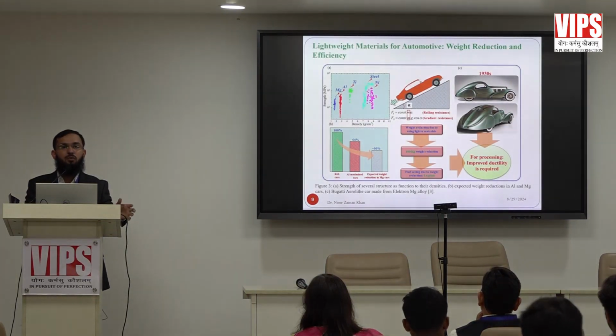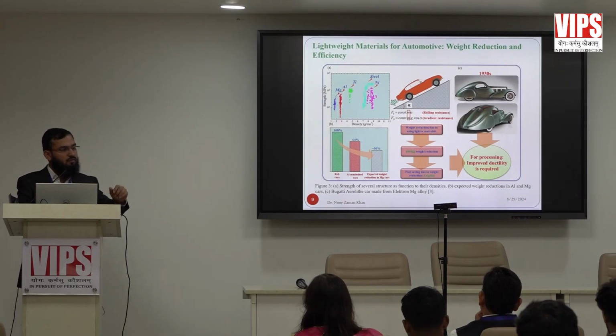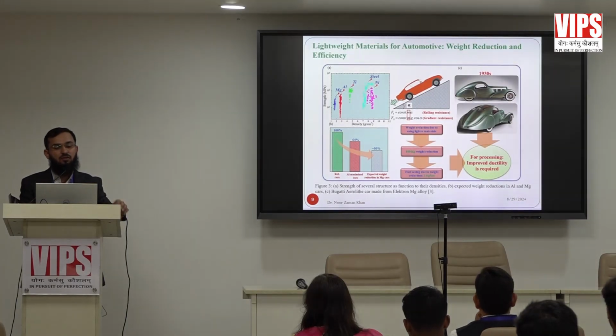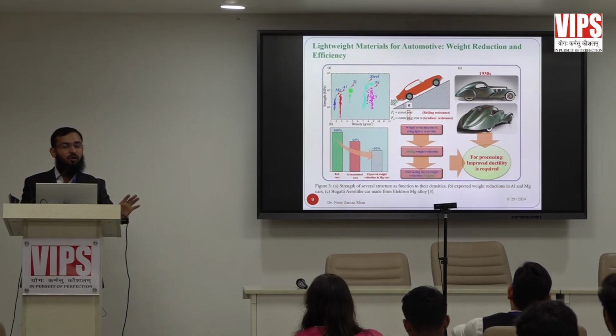So if we use aluminum by replacing steel or high density alloy, we can reduce the weight till we come up with 64% of the weight. If we use the magnesium alloys, we can further reduce the weight to 50%. In future, it is not yet highly used, because research is going on magnesium. We can use magnesium for reducing weight, but research is going on how to improve the strength.